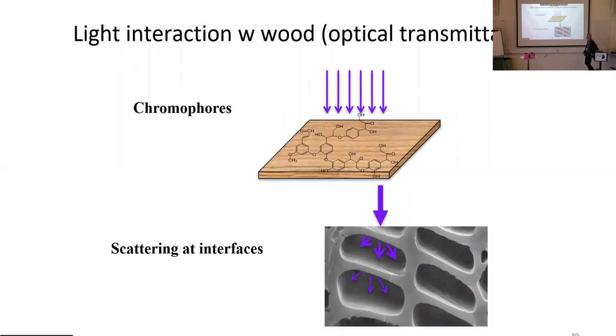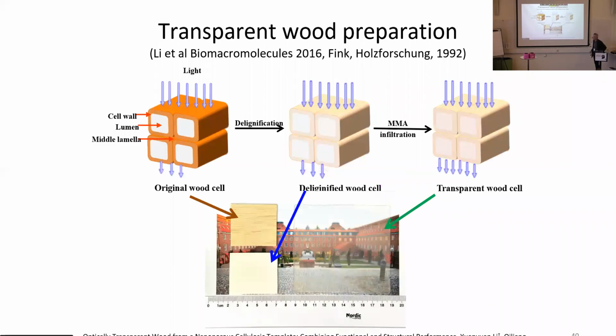The basic problems are that there are chromophores in lignin that absorb light by themselves. There is light scattering taking place at interfaces between the cellulosic cell wall and the gas in the center, so we really need to address that. By coincidence, I was scanning the literature. I found an old paper from the early 90s. A wood anatomy professor had developed a technique to study wood species by optical microscopy, and he made transparent wood. But he never thought about the engineering perspective of this. So this is what we have worked on. So basically, we impregnate with the polymers, we remove the chromophores, and we end up with a highly transmitting material.